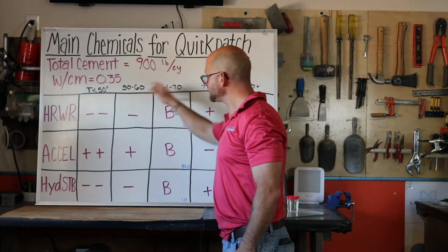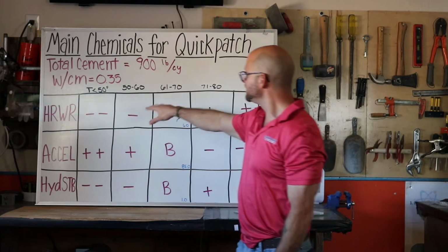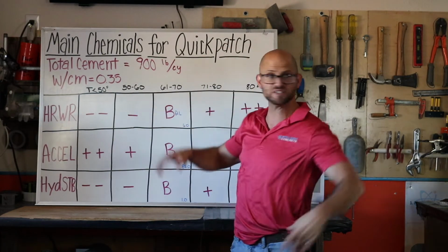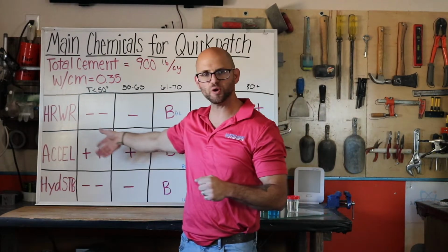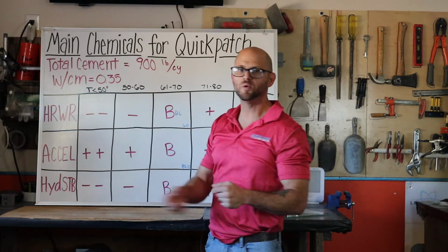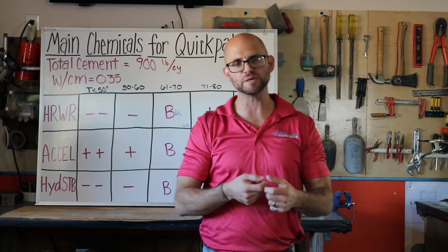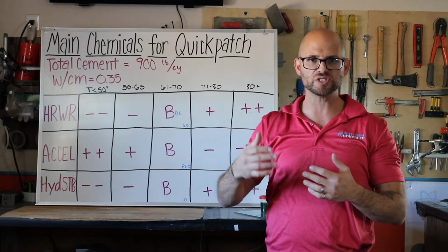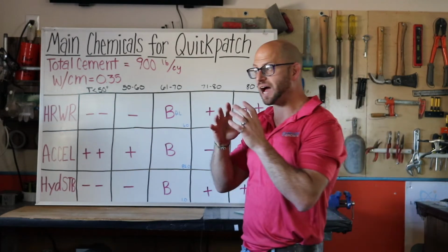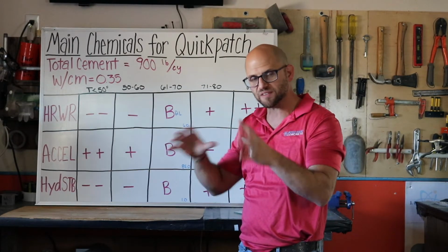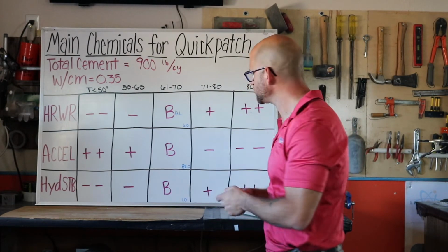And when I go down to 50 to 60 degrees, as opposed to 61 to 70, so going down 10 degrees, what I'm going to do is my temperature is going to be a little bit colder, my activation energy is going to be a little bit lower. I won't need as much high range to keep that fluid property because things aren't taking off as quickly.